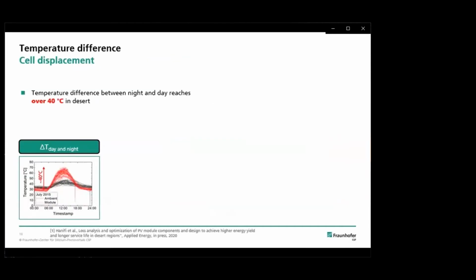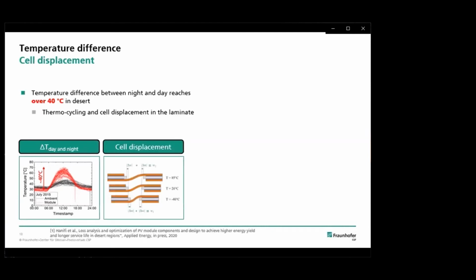Another thing I want to stress out or look at is the temperature difference problem, which causes some cell displacement. So between day and night, we typically have temperature difference up to 40 degrees in the desert environments, as you can also see from the environmental data, which is an example from Qatar in July 2015. And these temperature differences, which is effectively a thermal cycle, will cause a cell displacement in the laminate, as you can see in the example graph.